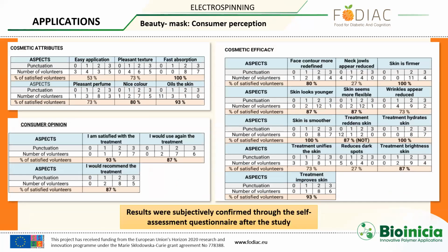The beauty of this as well is that after we finished this study, we gave a questionnaire to the volunteers about their perception. What did they think? Did they think that their skin looked better? Was the product good? Did it smell good, bad? Did it look good? And nicely, the quantitative data was matching with the qualitative data, in the sense that we observed that the wrinkles were reduced. Well, people could see that they looked younger in a way. From the commercial point of view, they also thought that the vast majority of the mask had a nice color, and the perfume was okay. So these are very good insights towards commercialization.